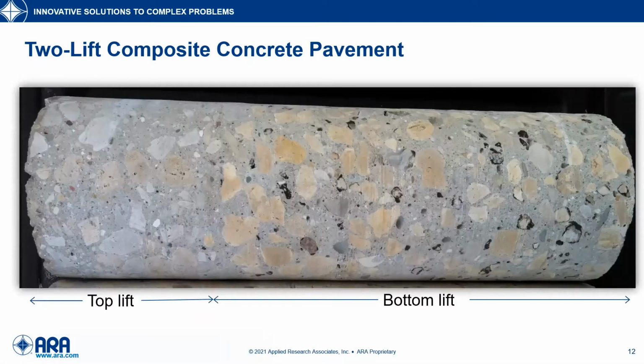So here is a core from that pavement. The concrete mix for the top lift required virgin coarse aggregate, while the concrete mix for the bottom lift required 15 to 50% replacement of the coarse aggregate with coarse reclaimed asphalt pavement. Those are the black aggregates you can see in the core. So the bottom lift concrete was commonly referred to as black rock concrete because of that coarse RAP. The bottom lift also required Portland cement concrete replacement with SCMs, fly ash and slag. Total replacement percentage was between 35 and 50%. The other thing this core shows is a well-consolidated top and bottom lift as it went through that paver.